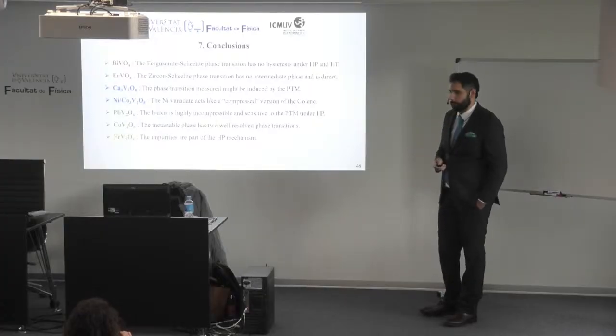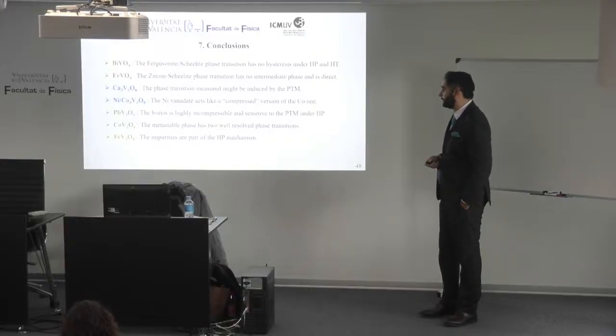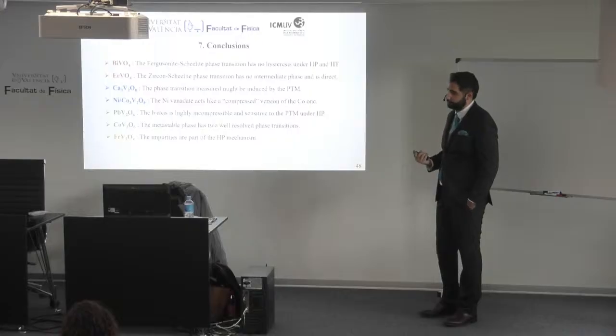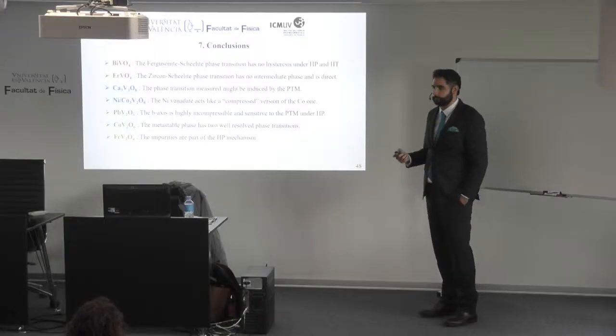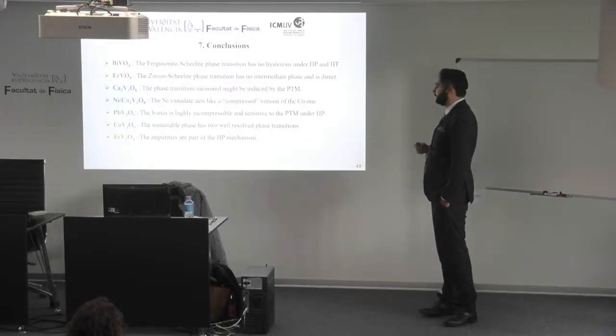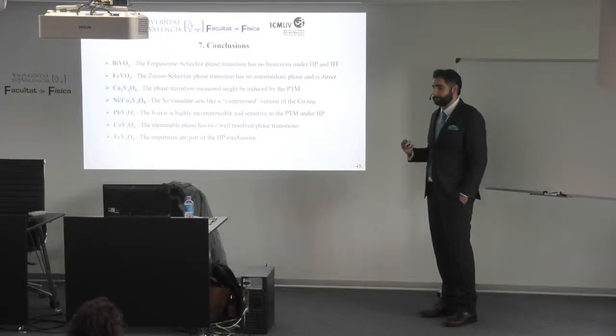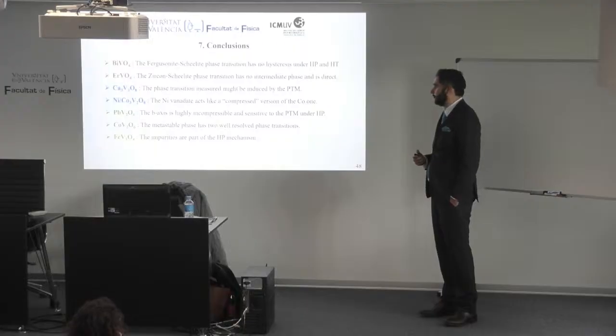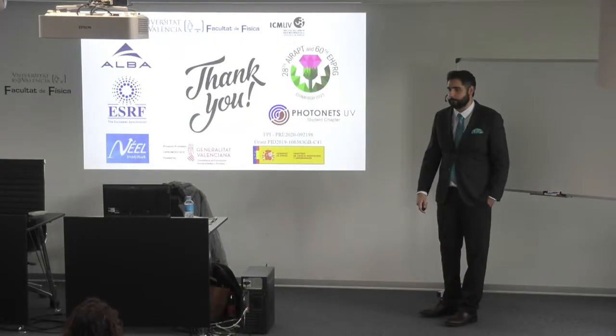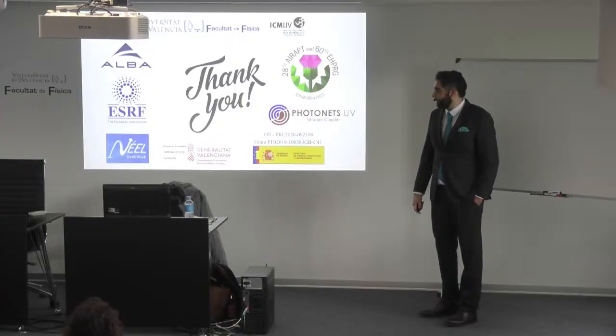For the metastable columbite cobalt metavanadate, we discovered 2 new phase transitions, one isostructural, with the very useful information of the single crystal signal, and another one to a monoclinic structure. And finally, the spinel iron vanadate has impurities in the sample, but in the end were part of the pressure mechanism of the sample. So this is everything. Thank you, everybody, for being here, and that's all.